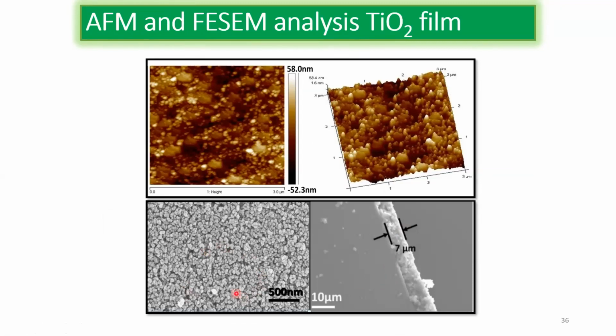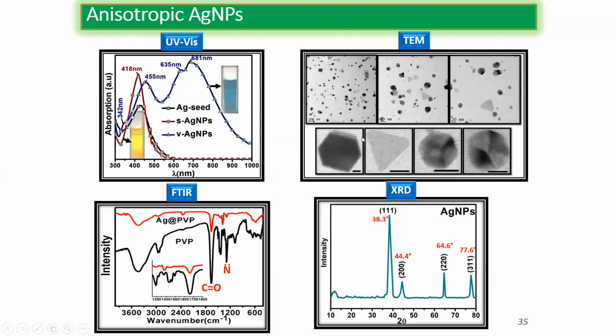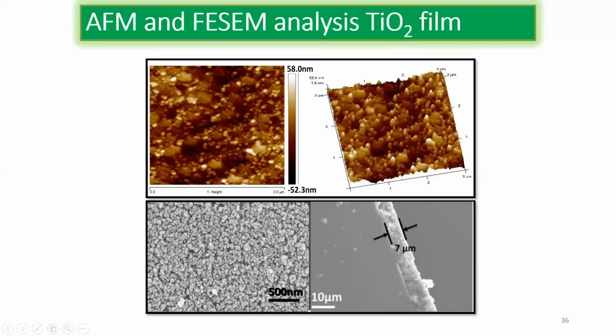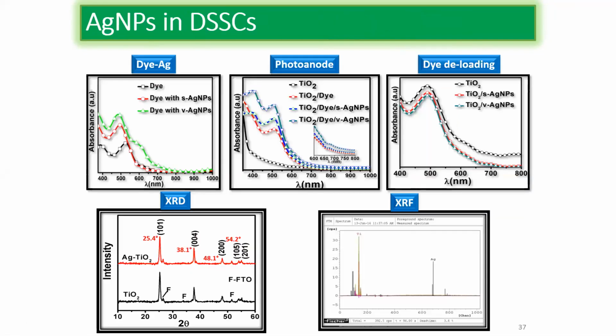These are TiO2 nanoparticles, and I am going to load the silver nanoparticles I synthesized over this TiO2. It is a porous structure of around 70 nanometers. The silver nanoparticles go inside this matrix, inside this 7 micrometer film, and I'm going to test the theory I explained earlier, whether it is going to work or not. To test the silver nanoparticles, I mix them with the dye molecules that I have used.